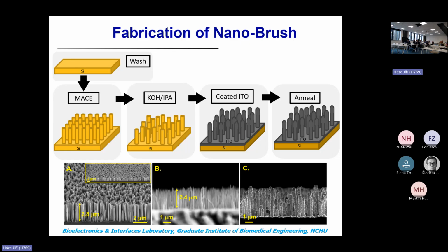And you can use the KOH with IPA solution to reduce the nanowire density. After you reduce the density, it depends on your needs. If you want to sense micrometer scale material, maybe you can make a very dense structure. And if you want to sense nanoscale material substance, maybe you can make them like a nanobrush structure with some distance.